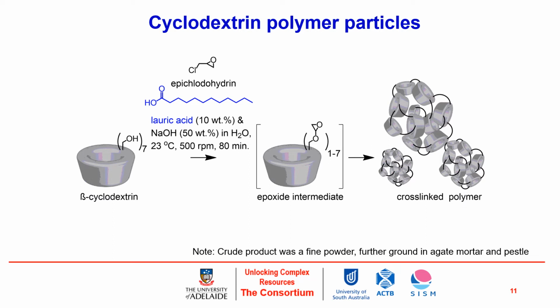So to make this utilizable and applicable to analyses that could be conducted to evaluate its interaction with interflow components, I first had to produce a polymer, so something tangible that's not going to dissolve in water that I can expose to these components and still measure their properties. To do this, I generated a reactive intermediate of beta-cyclodextrin by converting the hydroxyls of the hydrophilic rim into an epichlorohydrin epoxide. And with this epoxide, I was able to then cross-link these polymers.